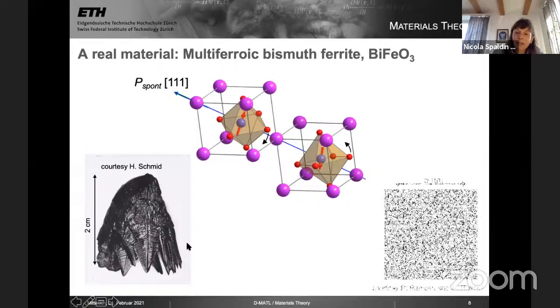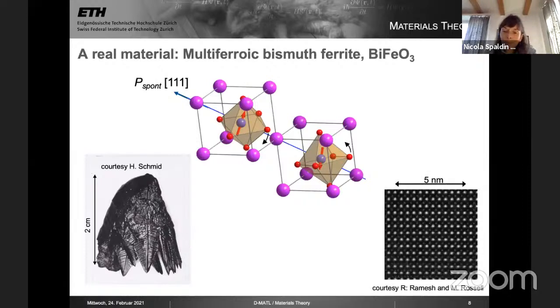And it was really only in the early 2000s, largely through the group of Ramesh, that they succeeded in growing bismuth ferrite thin films. So this is a high resolution transmission electron micrograph from Marta Rossel, who's now at EMPA. And you see here the very bright white dots are the bismuth atoms.